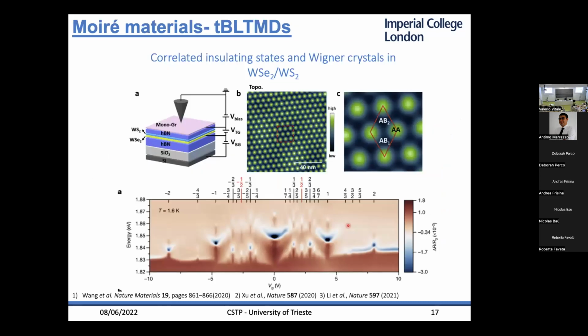In a different system, in WSe2 and WS2, so tungsten diselenide or tungsten disulfide, which have a slightly different lattice constant, this is an optical experiment where they show that at different values of the filling, you have several correlated insulating states. And some of these correlated insulating states have then been identified as generalized Wigner crystals. So these are real STM images of electrons localizing in these spots and forming these charge order states.